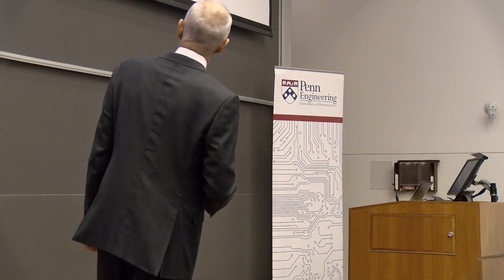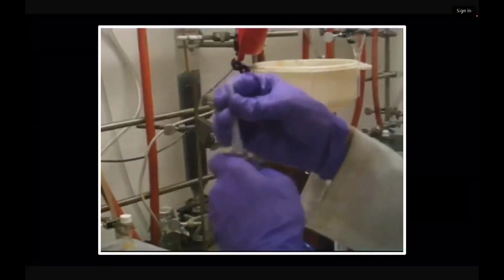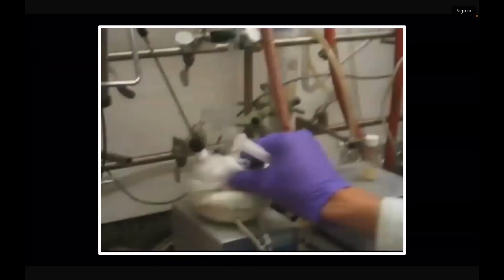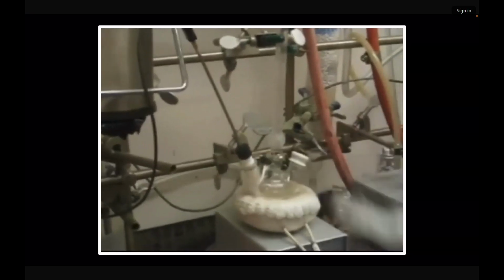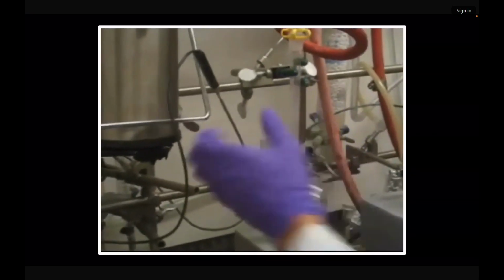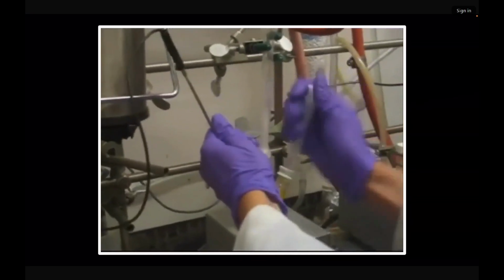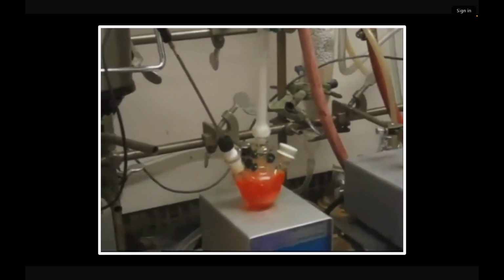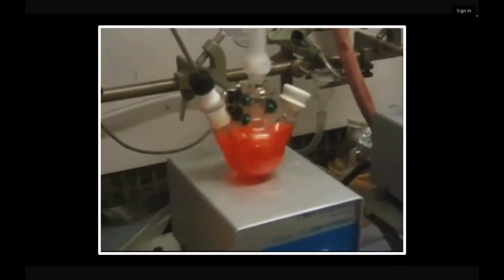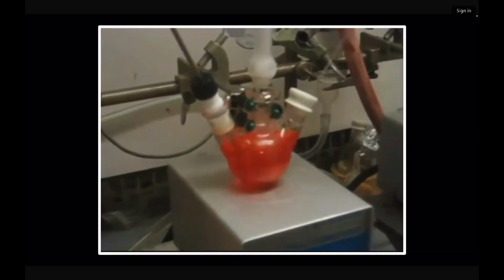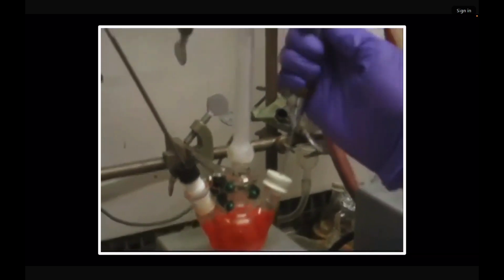Okay, and this is what it looks like. So you've got the precursors. This is at 300 degrees Celsius, this flask here, and then you have the quick injection, and then the nucleation. So this is at high temperature. So these particles are probably less than a couple nanometers in diameter. And then it keeps growing, so that's nucleation, then the growth step. And then we're going to skip 20 minutes here. It's going to turn much darker. So we've skipped about 20 minutes of growth.